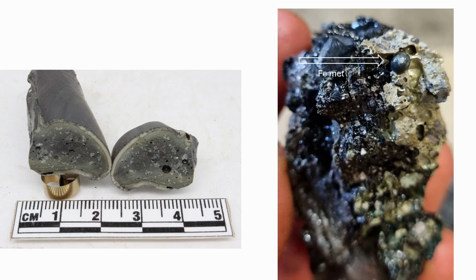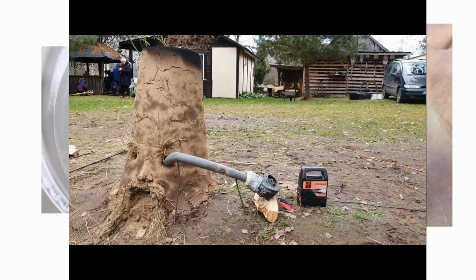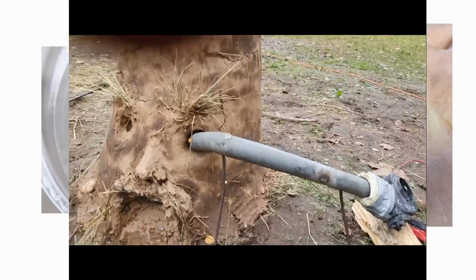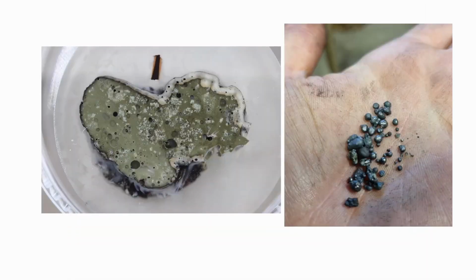To promote slag flow, we initially intensified the blowing and raised temperature. However, higher temperatures can lead to excessive carbon in the iron, even resulting in cast iron formation. Additionally, strong blowing and elevated temperatures increase the phosphorus content in the iron. To prevent iron carburization, we implemented countermeasures, such as reducing the fuel-to-ore ratio.